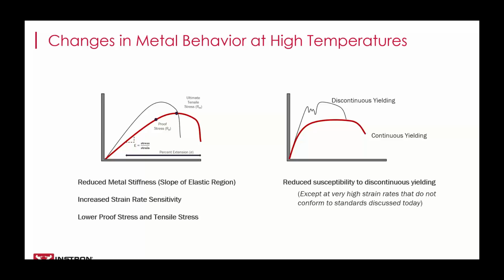So, one of the things that I've found is that when setting up your high temperature testing equipment, it's really helpful to understand what's going on with the material itself as you heat it up and run your test. So let's take a look at how the mechanical properties are actually changing as the temperature increases. We know that increasing temperature of the metal increases the vibration of atoms in the crystal structure. As they vibrate, this increases their atomic distance. And because the distance between the atoms is greater, the atomic force that holds them together is weaker.